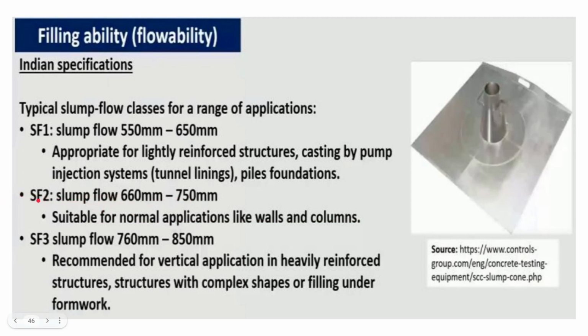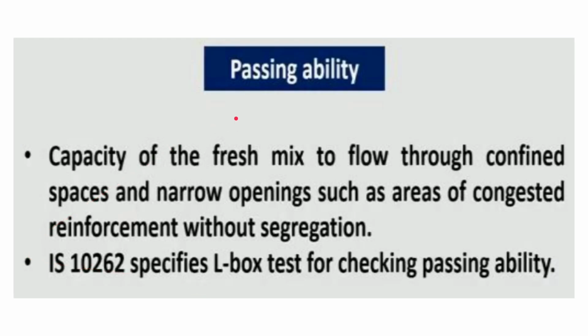so that is categorized as SF2. And if we need it for vertical applications in heavily reinforced structures with complex shapes or filling under formwork, where there is very high density of reinforcement and other complex shapes, we have to have a very high slump value, which comes in the SF3 category, where the slump value is from 760 mm to 850 mm. These are the types of slump flow ranges. So that is all about filling ability or flowability.